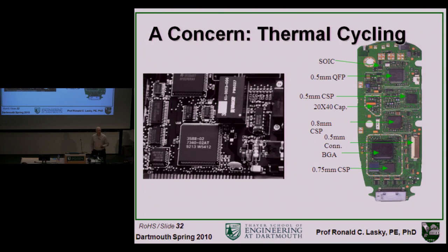And usually it's very strong. Like something like the cell phone, they'll actually expose it to like minus 65 C to 100 C. They'll literally put it in something almost like liquid nitrogen, well, not liquid nitrogen, but dry ice temperature to boiling water, back and forth, to make sure that the thermal shock doesn't break any of the solder joints here.